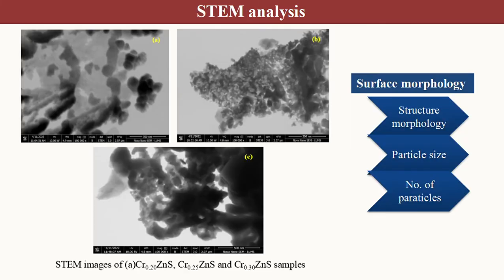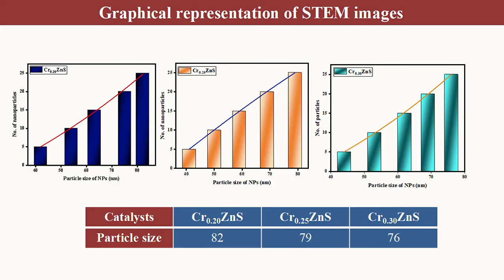The next analysis is STEM. The STEM analysis provides information about the surface morphology of the samples. The dark area in images A, B, and C shows the maximum density of nanoparticles. Apart from this, the particle size is also calculated from it. The values of average particle size of all catalysts are shown in graphical representation.